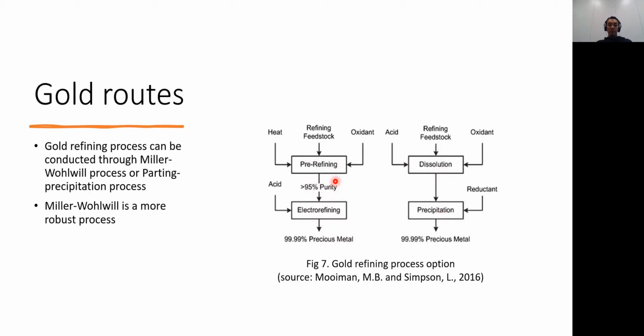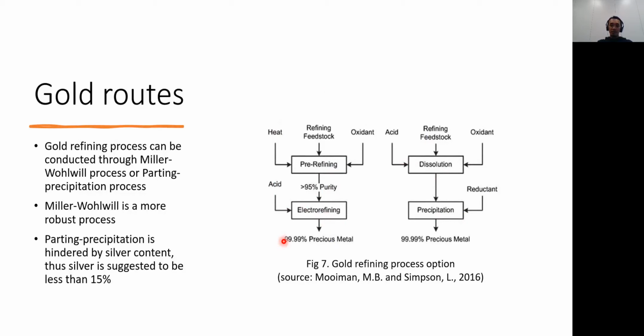In this flow sheet, the pre-refining process is mainly called the Miller process. Miller is a dry chlorination process, and the electrorefining is called the Wohlwill process. The Miller-Wohlwill process on the left side route is actually a more robust process compared to the right side because it has higher kinetics: smelting, then adding chlorine gas, and then electrorefining. Also, the right side process has some difficulties processing bullion that has more than 15% silver. We will go through this in a few slides. So this one has higher kinetics, and this one has a limitation on the content of the bullion it can process. So for me, it's a no-brainer. I think the left side route is the best of these two.